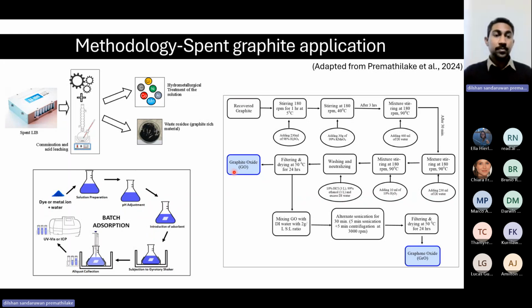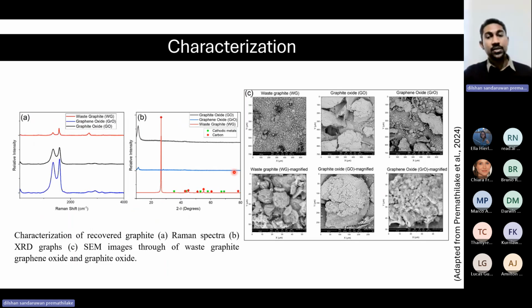Here in this slide, I'm going to show you the characterization and optimization of my materials. In graphs A and B, you can see the Raman spectra and the XRD patterns of the two materials that I produced. The red one shows the waste graphite derived from the recycling process of spent LIBs. Here we can identify that the graphene oxide and the graphite oxide are largely changed from the waste graphite. This is because the oxidation gives lots of delocalized carbon atoms. This is why the D peak, the first peak, is quite a bit higher than the waste graphite.